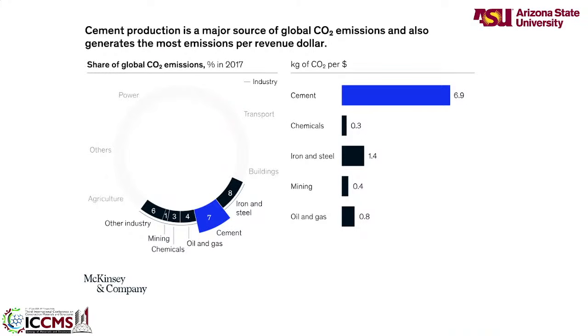And if you look at global carbon impact, cement production generates the most emissions per revenue dollar. Again, this is beautiful math where you increase the denominator and you get a small value, or reduce the denominator and get a lower value. People use this nicely, and if you're a consultant arguing for somebody who doesn't want to show concrete in good light, you can use a very small denominator. But generally, you see that per revenue dollar, kilograms of CO2, cement has the highest value. Even iron and steel, which has to go to a much higher temperature, has a much lower value, but steel is much, much more expensive than cement.